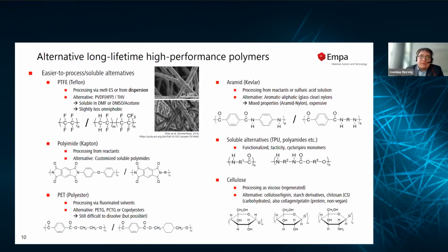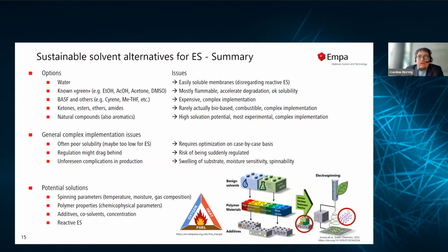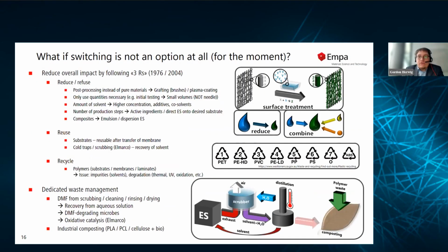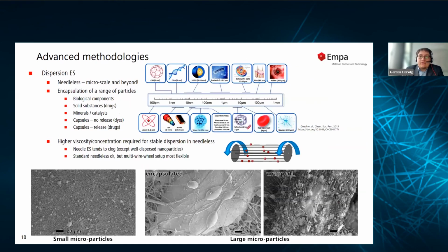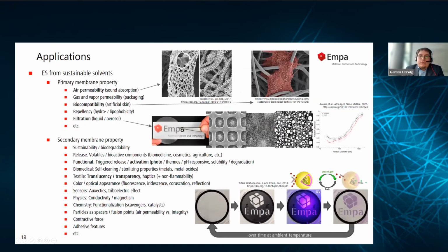Sure, that's known. I mean, it depends on what sort of mixture you have. Something very interesting that we've been working on previously, but not using green solvents whatsoever, was these very porous particles here. So in this case, the more humidity you have, the more phase separation you have, and that's where you can get these structures. But again, in this case, often you have to go via chlorinated solvent, so that's not very great. What you get instead is the more you increase the humidity, the more bumps and wrinkly structure you get. So not quite as much as here, that was post-processed, but it can look relatively rough.